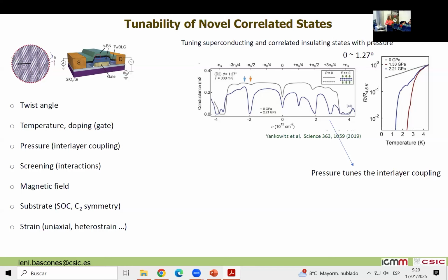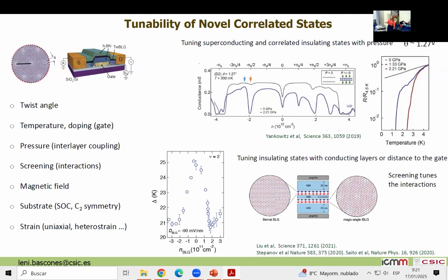Well, in general, the interactions in a system are going to be affected, let's say, by screening. So people can play a bit with having, for example, the gate closer, but there are also some ingenious ideas. Here, what they did was they have a twist bilayer, and they put close to this twist bilayer another bilayer graphene, standard Bernal bilayer graphene. Then they charged this Bernal bilayer graphene, and in this way they tune the gap of the insulator, something like charging that with electrons. So they were able to tune that.